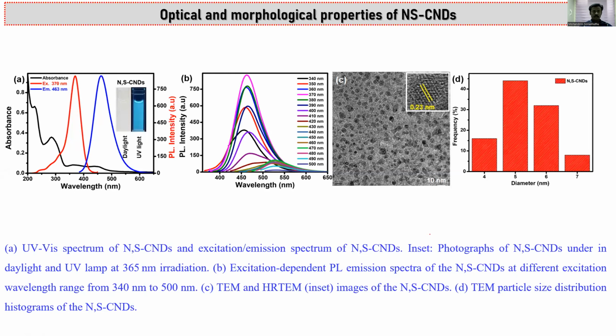On the other hand, in photoluminescence we can get 463 nanometer. The blue line is 463 nanometer, and this one is the excitation spectra at 370 nanometers. The highest intensity we can get is around 800 or 900 something. The solution is colorless, and after using the UV light we get a bright blue emission, which we can also see from this.